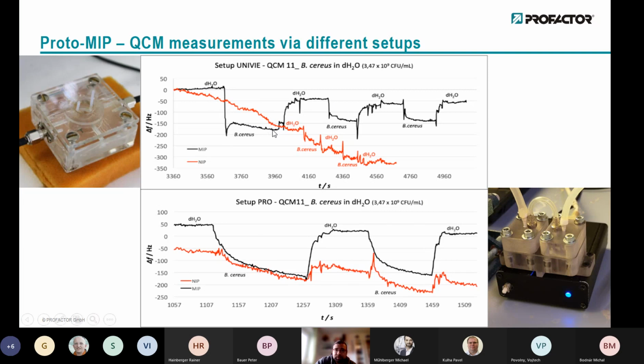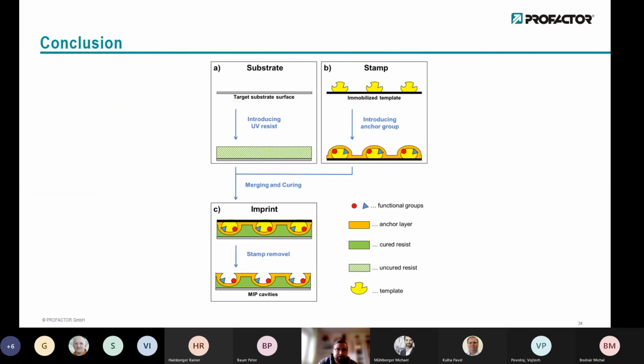The good thing is that it's reproducible, meaning it's reversible, meaning that you can wash out the bacteria, introduce them again, wash out again, and introduce them again. And on our own setup, the same was done, and this gives comparable results. So here we have around 150 to 200 hertz in frequency shift, which we also achieved in our own setup. So this is quite comparable using the same amount of bacteria.